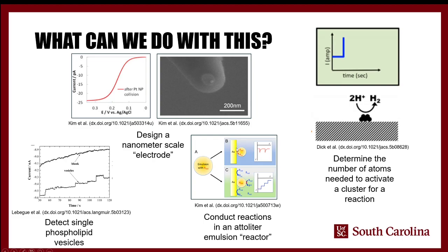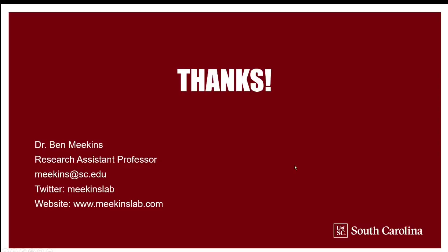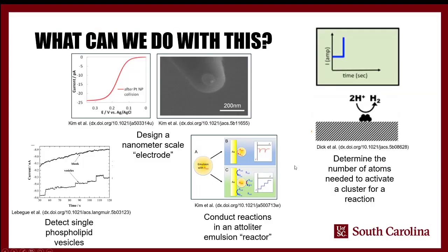And so that gives you information not only on the size of the pocket itself, but how quickly your reactant inside of it diffuses to the surface to actually carry out the reaction, and how long it takes to consume everything in there as reflected in a transient. And so you can actually fit that and extract information again about the kinetics, about the diffusion rates, and even about how much of your reactant was present in the reactor itself.